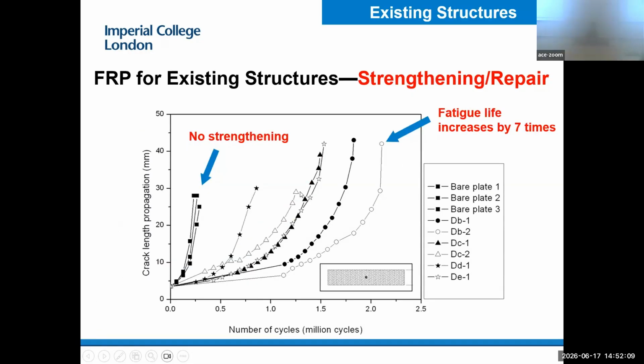So this is the testing results. As you can see, for the steel plates without FRP strengthening, we can find out the fatigue life - this is the crack length at failure and this is the corresponding fatigue life. The other curves correspond to specimens with different strengthening configurations. As you can see, it's very effective - we can increase the fatigue life effectively by 7 times.